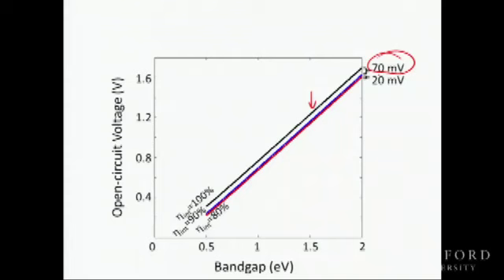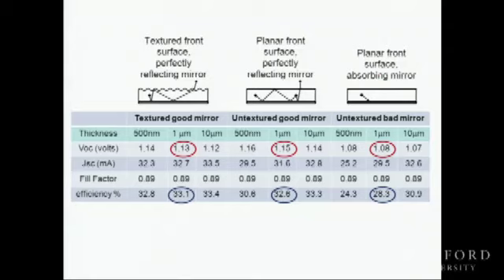And so here are some calculations of what to expect. And I'd like to contrast what's going on here between two situations. This is the situation if you have a good mirror, let's say a 100% mirror, versus a bad mirror, a 0% mirror. And notice the difference in the open circuit voltage. So the mirror quality, surprisingly, has a tremendous effect on the open circuit voltage.